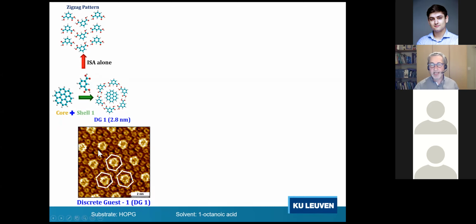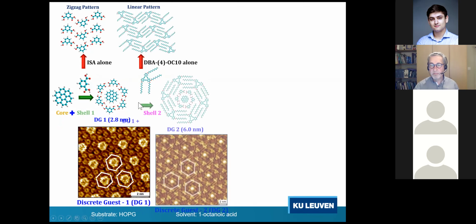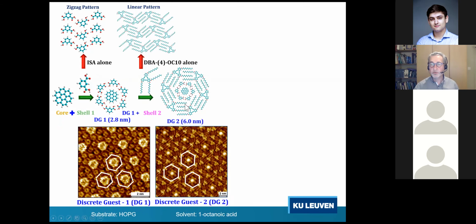If you then make a mixture of the coronene, the shell 1 molecule, and the shell 2 molecule, well, this mixture leads to a 3-component network. I show it here in the cartoon. You have the coronene molecule surrounded by 6 isophthalic acid molecules, so the shell 1 molecules, and then surrounded by 6 of these shell 2 molecules. And indeed, also in these STM images, you can recognize that.